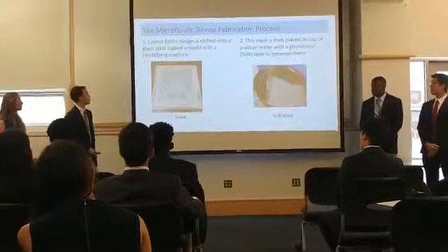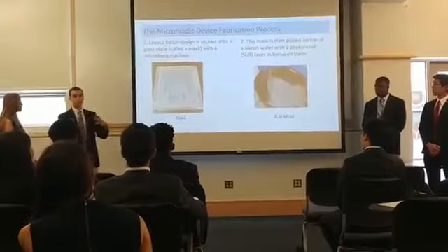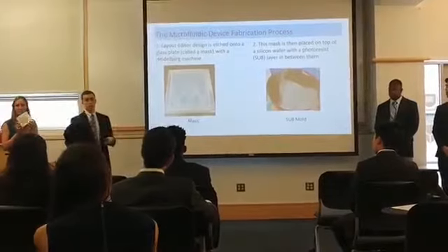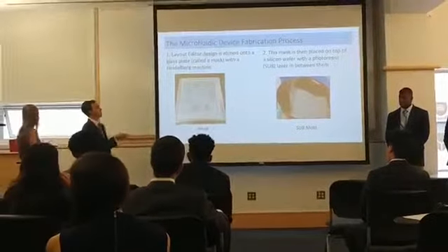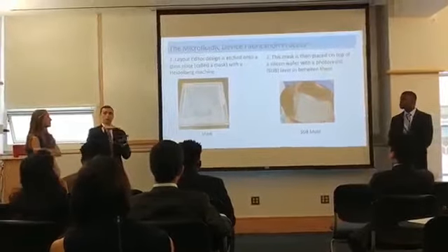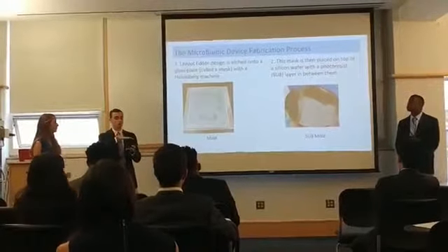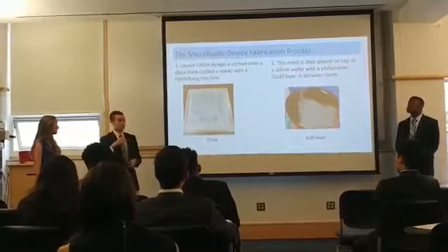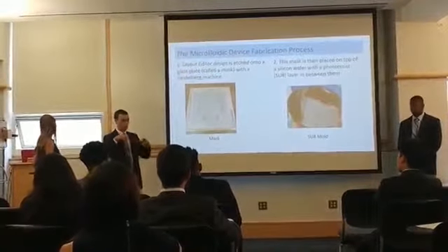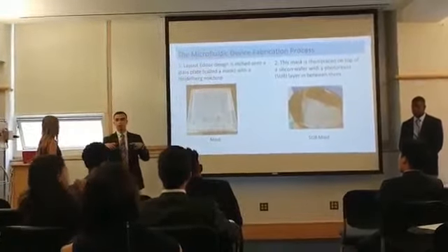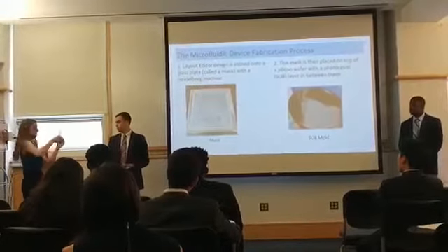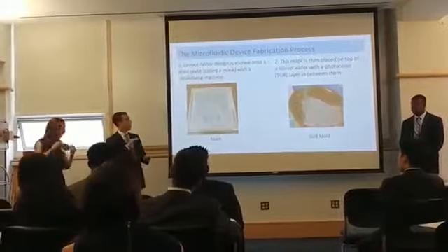So the fabrication process starts with a glass mask. It's just a piece of glass, and this Heidelberg machine etches whatever design you want onto the glass. Then the next step is that this mask is placed on top of, there's a silicon wafer on the bottom, then there's a photoresist layer, which is SU8 in our case. It's put in between them, and then the glass plate on top. It's treated with UV light rays. And then, essentially, the photoresist reacts where it sees light and bonds to the silicon wafer on the bottom, which is right here. We'll pass this out at the end.